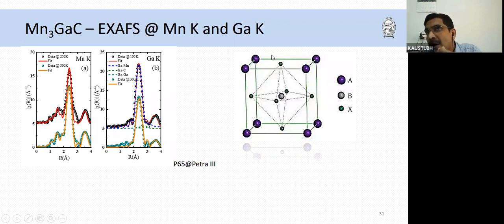So it may not be possible to separate out the two just from one edge, one EXAFS fitting, especially if you are trying to look for local structural disorder. So we thought we should also do the gallium edge, because from the gallium edge, we will get the gallium-manganese distance, which we can use as an input for the manganese EXAFS, and then extract the manganese-manganese distance.